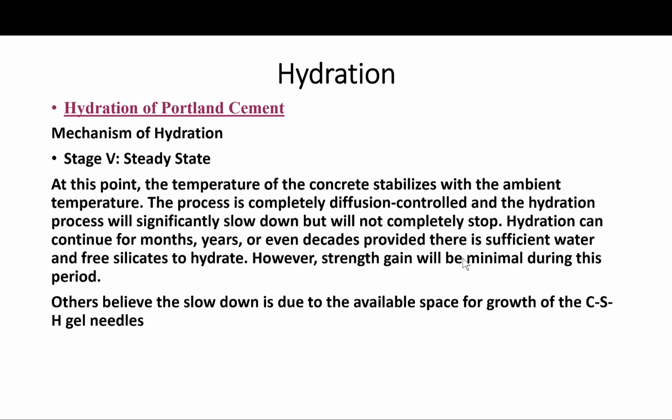Okay, with regard to the diffusion control though, some other researchers believe the slowdown is due to the unavailability of space for growth of calcium silicate hydrate gel needles, not entirely due to the diffusion control process.